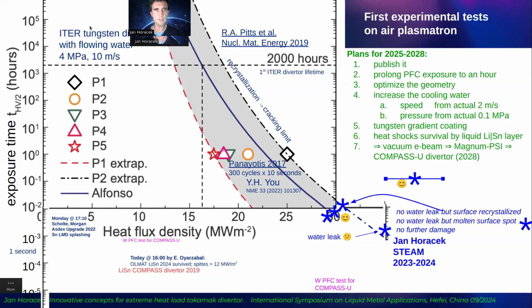well-known graph for the ITER tungsten divertor, where you have flowing water with 4 megapascal pressure and 10 meters per second. You have such a dependency of the time, exposed time, in very strongly logarithmic scale with respect to heat flux density. And these are the measured data. So in fact, if you expose it with plasma for 1 hour, it can sustain at maximum 25 megawatt per square meter, and then it would crack due to recrystallization and the length of the exposure. And this was measured by 2 different groups.